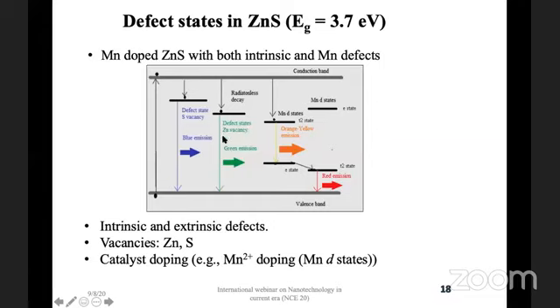And for the case of zinc vacancies, we get green emission, which is 520 nanometers. Usually, zinc sulfide is one of the oldest semiconductor materials as well, already used in fluorescent materials to produce green light, because we have more zinc vacancies than sulfur vacancies. But if we dope with some other impurity, like in our case, we have doped with manganese or with tin, we introduce impurity states, which gives us another band in the yellow or red part of the spectrum. So that's important.